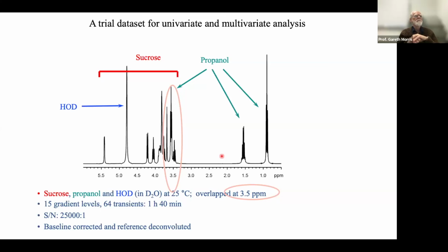And I won't have time to talk much about this today, but something that's very useful for getting good, clean diffusion results is a data processing method known as reference deconvolution. Unfortunately, it's not well implemented in all NMR software, but it is an excellent way of curing many sorts of systematic errors, for example, frequency drift, line shape error, low frequency modulations, and so on. So we use reference deconvolution a lot in DOSY to ensure that all of our spectra measured with different gradients have the same instrumental line shape.